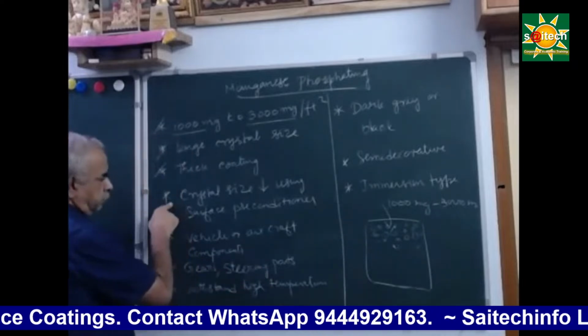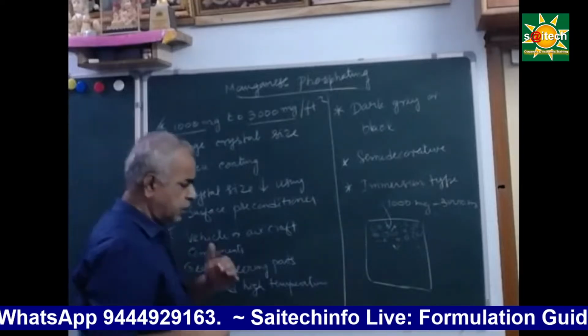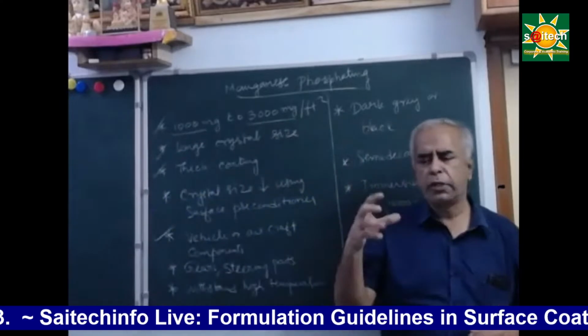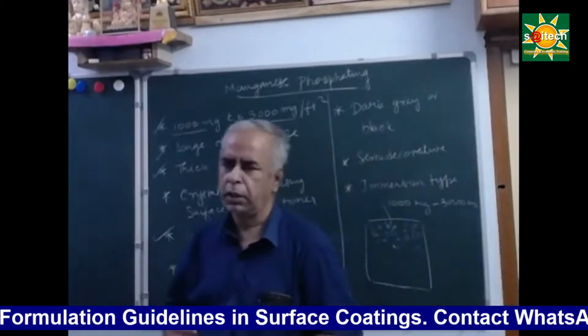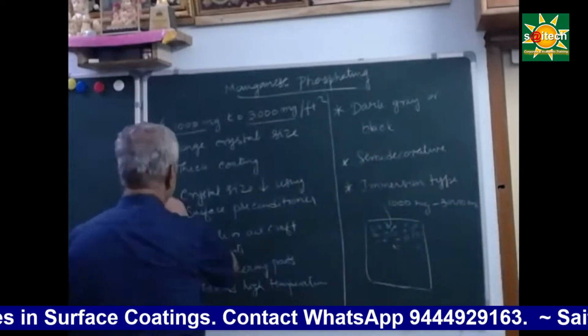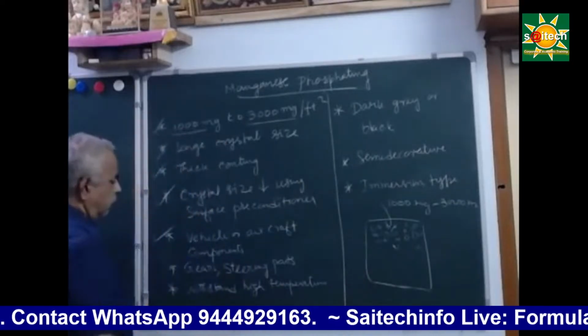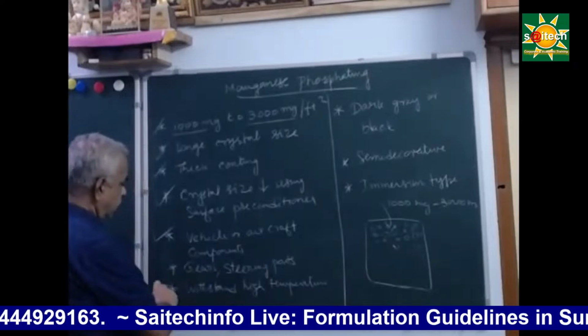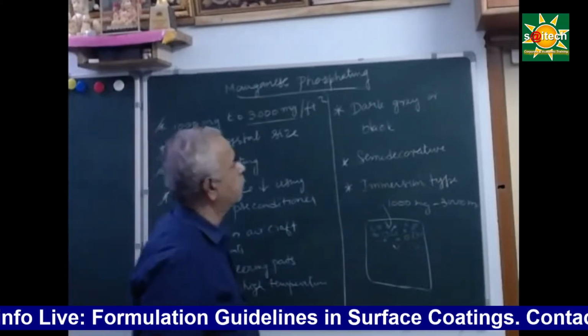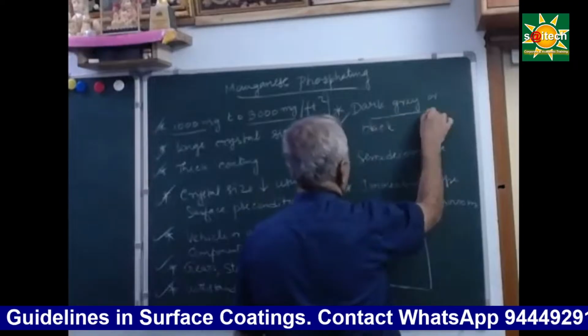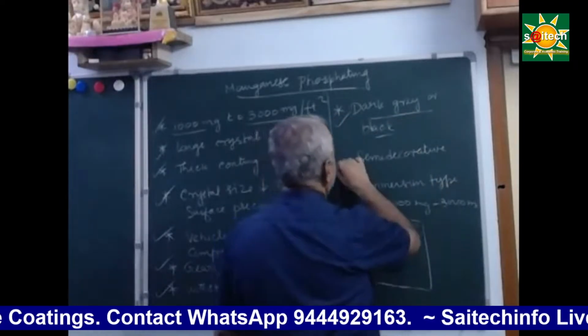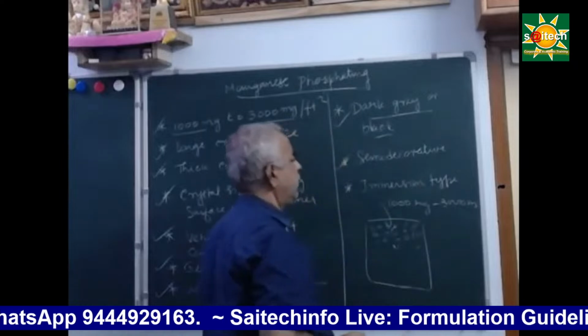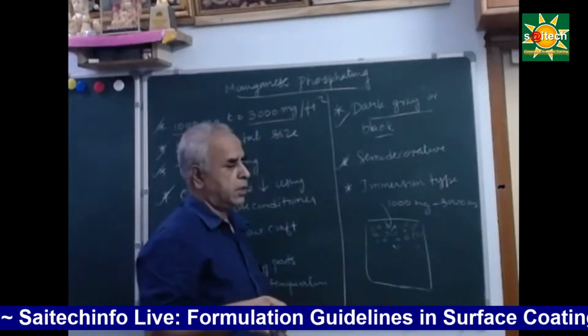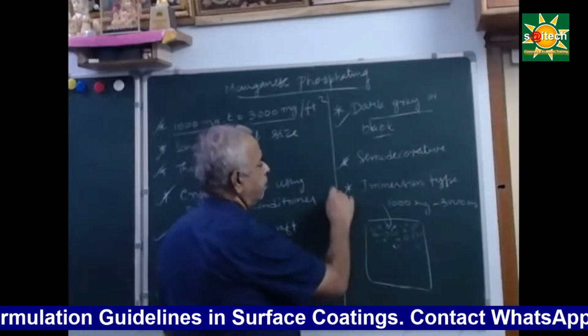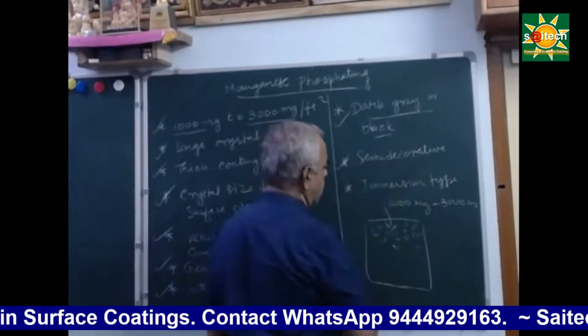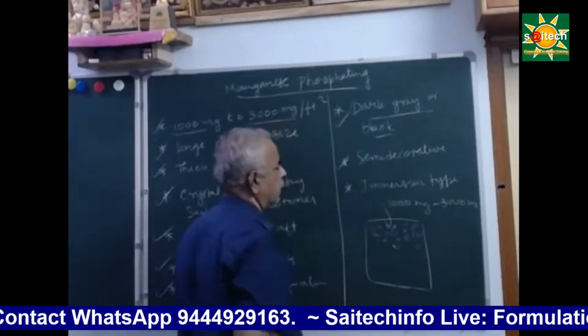If you want to reduce the particle size, you can introduce a surface conditioner prior to the phosphate bath. It will withstand high temperatures very well. The color will be dark gray or black. It is sometimes semi-decorative only, but you can leave it as such by oiling. As I already suggested, no paint coating is recommended, but oiling and greasing can be done.